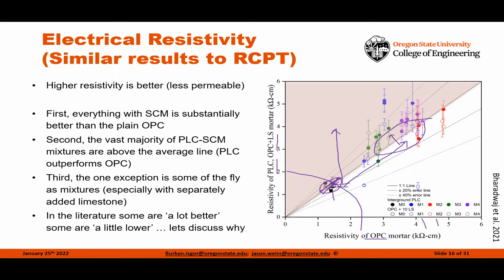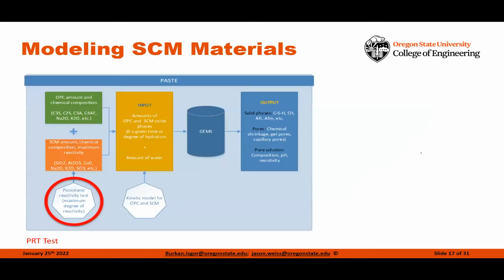So how do we describe this in the system? Well, the first thing to note is the porosity of these systems is about the same, although it may be 2 or 3% higher. But the connectivity of the pores, which is a combination of the tortuosity and the constrictedness of the pores, decreases substantially in these systems. So we're actually seeing a huge benefit in terms of transport, a huge benefit in terms of service life, simply because we're using the SCMs and because we're using the SCMs with limestone in the system.